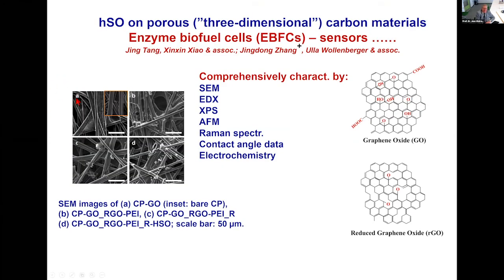Then Jing Dong's PhD project was dealing with porous carbon materials, exploiting the conversion of graphene oxide to reduced graphene oxide, reducing the number of surface functional groups to a minimum. The idea is graphene oxide is tractable in aqueous solution. It's soluble, whereas graphene or reduced graphene is not. So you do all your manipulation using graphene oxide. You combine it with molecules in solution, put it all up into your structures, and then you reduce the graphene oxide. Then you go from a less conductive to a more conductive surface material.